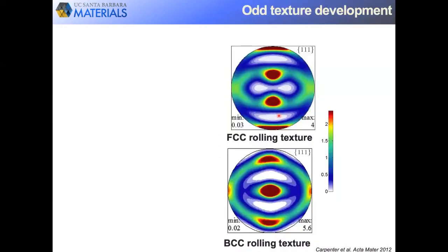or pure niobium. So then next, we analyze this nanostructure itself. It is interface dominant. We've established that. We wanted to examine other aspects of the nanostructure to see if we retain this familiar structure that we would expect from rolling. So first, as I mentioned, the nanolayers are spanned by one grain, and anytime we have 200 nanometers and below, just one grain is spanning this layer, so they are interface dominant physically.